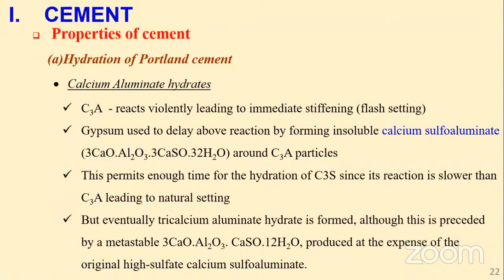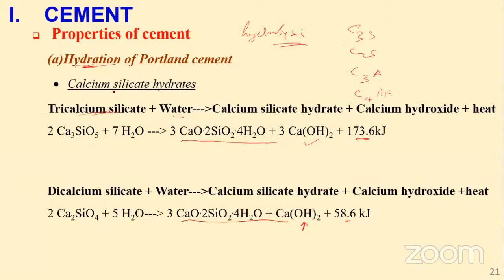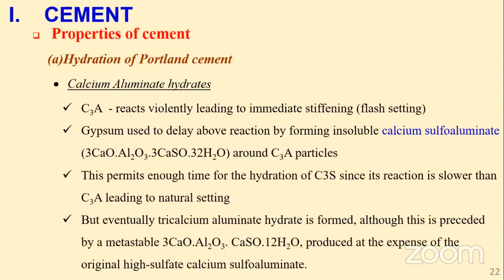Now, calcium aluminate hydrates. So the first ones that we are talking of will form calcium silicate hydrate. When calcium silicate, either di or tricalcium silicate, comes into contact with water, they are hydrated to become calcium silicate hydrates. In a similar manner, when calcium aluminates come into contact with water, they are going to form what you are calling calcium aluminate hydrate. Now, as I stated earlier, tricalcium aluminate reacts very violently, which will lead to immediate stiffening, which we call the flash setting.